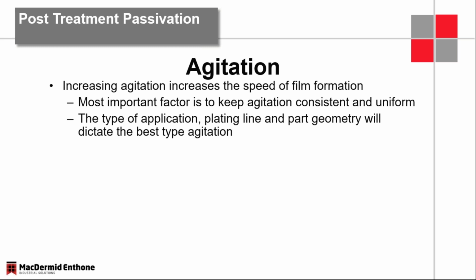So what's happening with the agitation is the precipitation in that very, very thin interface between the zinc and the acidic Passivate solution. That interface needs to be changed over very, very quickly, because once that chrome precipitates, you want to get more chrome in that area again so you can keep building that film. If you don't change over that interface layer, you will not have a good Passivate film. You won't have the proper color, and you certainly won't have the corrosion resistance that you're looking for.